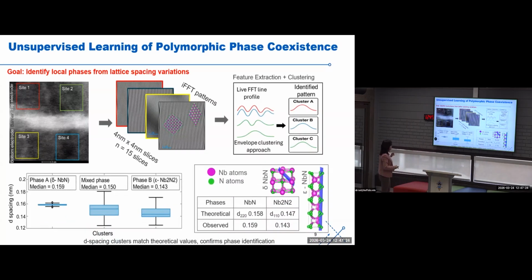What does it mean? So when we apply the feature extraction and clustering, we can see 3 different regions, and we can extract the values for each region. We can see the values here, right? Now, theoretically, we know for these 2 different phases of niobium nitride, which was used for the electrode, the theoretical values are matching with the observed values, which are phase A and phase B. And this one is the mixed phase.